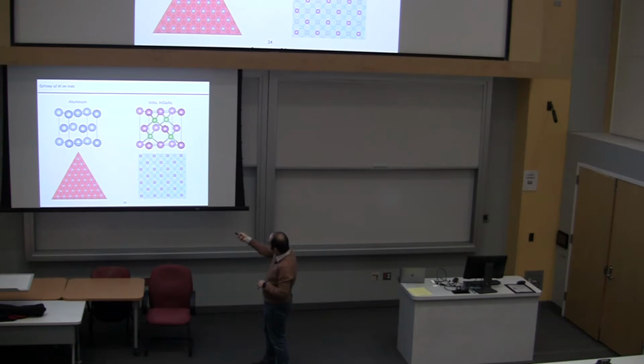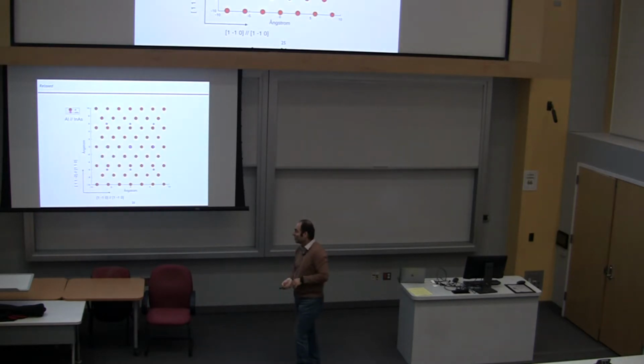This is your zinc blende, and this is aluminum in a 111 direction. Aluminum is FCC, but for this particular facet we are looking at 111. That's why it looks hexagonal, right? So you can just put it on top and see how it looks. That's how it's going to look. The reds are aluminum, the blues are indium arsenide, and there is no lattice matching. This is by definition, and you see things are kind of wandering around. Indium arsenide lattice constant in this plot is like 6.1, right? Now let's allow that lattice parameter to change a little bit. If you have gallium, for example, the lattice constant is going to shrink a little bit.